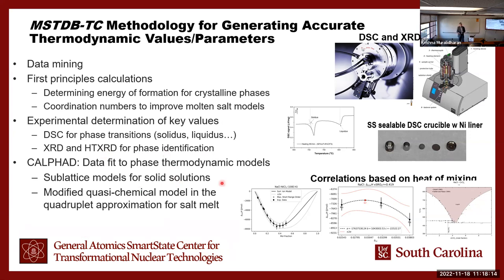So we model the phases, the solid solution phases, the liquid melt, and we get values for the compounds, stoichiometric compounds, vapor species, et cetera. The information is high temperature XRD and DSC curves. These salts are extremely sensitive to moisture and oxygen, so the least bit of contamination screws them up. You get polymerization, et cetera. If you get the melting point right, the salt is good, because it's a very strong effect. So here's a DSC curve, and then we often have to do correlations. We don't have the exact information for a system, but we have information for related systems.